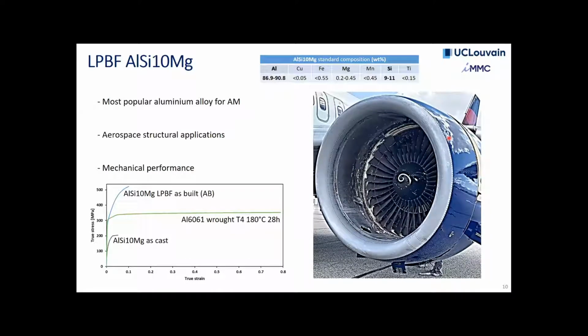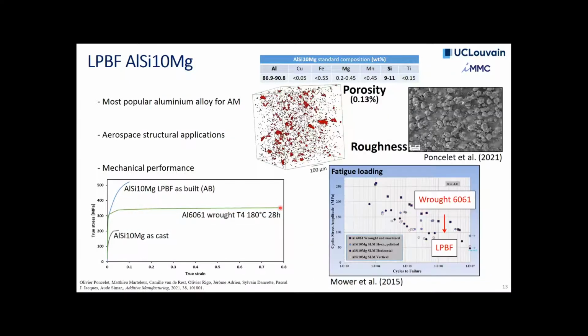Now, if you compare these alloys to the 6061, which would be considered as the raw alloy used in these types of applications, you can see that the ductility of these alloys is much lower. And that is definitely an issue when you have applications where damage resistance matters, so you should have materials that are ductile to be able to sustain, for example, bird strikes, as you can see in that particular bad situation in this image here, where you have failure of the fans. So this is definitely an issue, and we should improve the ductility of these alloys, not to form them, because we don't want to form them, they're already formed, but to improve their ductility and crash resistance.